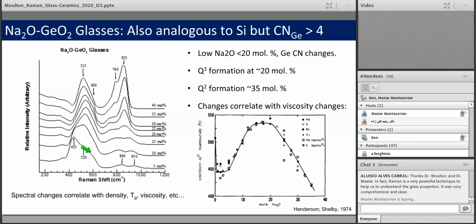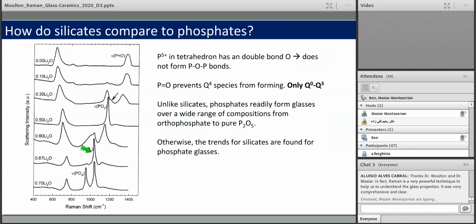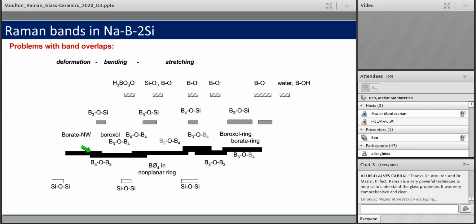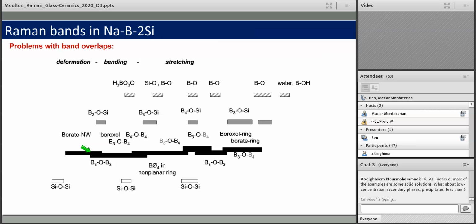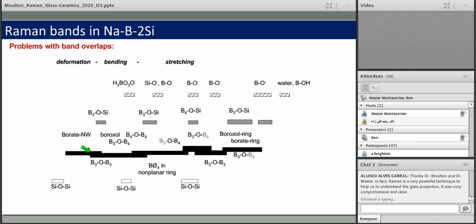The same goes for borate, boroxol rings, trigonal boron in threefold coordination versus tetrahedral boron. To my knowledge, and I have not worked on borates, you can see in this graphic here where you would expect vibrational modes from B3, trigonal boron, and B4. And you can see that the B3 vibrations are typically at lower frequencies than the B4 vibrations here in the middle or here.